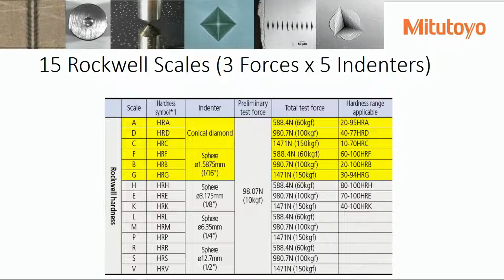So 15 scales with just 3 test loads. The Rockwell is 60, 100, or 150 kilograms, and you change the indenters from diamond, 16th inch ball, 1/8 inch ball, 1/4 inch ball, 1/2 inch ball, and you get the 15 Rockwell scales. Okay, so if you have a Rockwell machine, it theoretically is capable of all 15 scales. You might not have all indenters to start with, but it's capable of that.